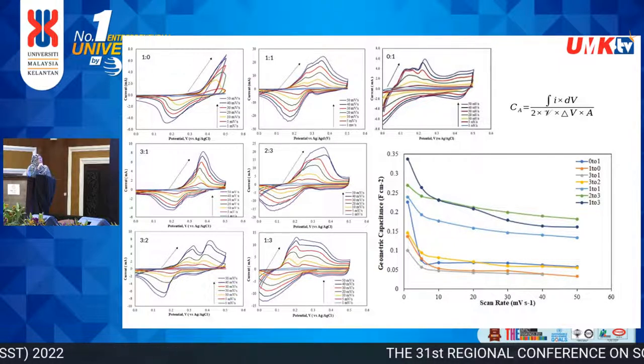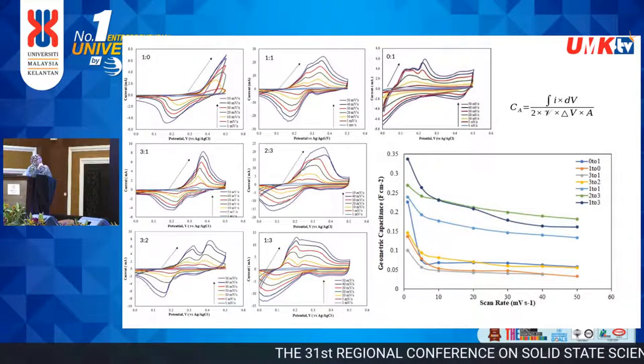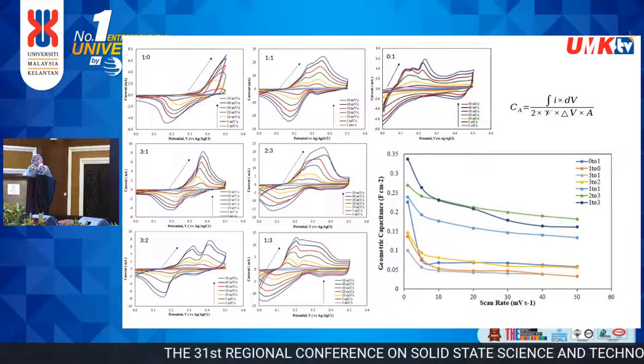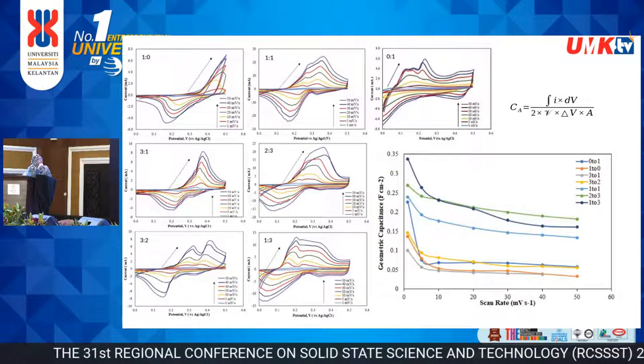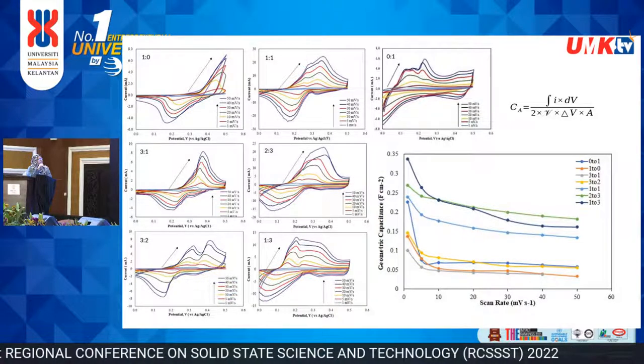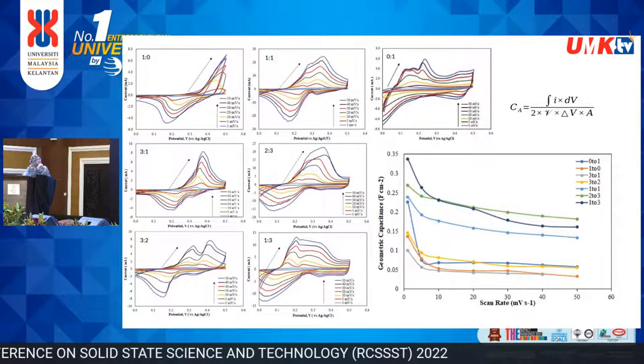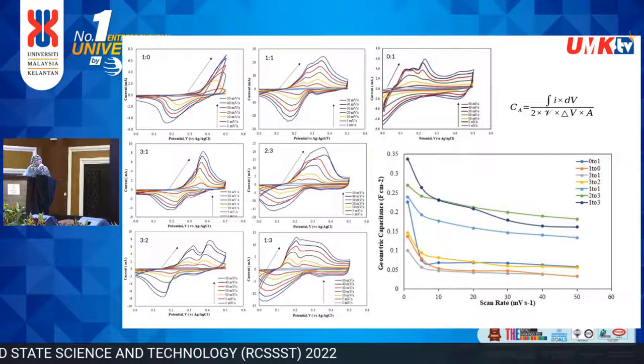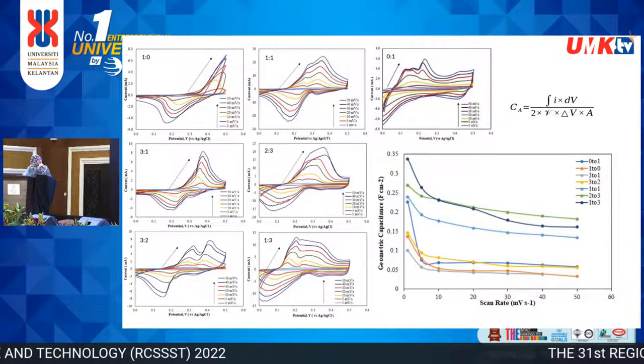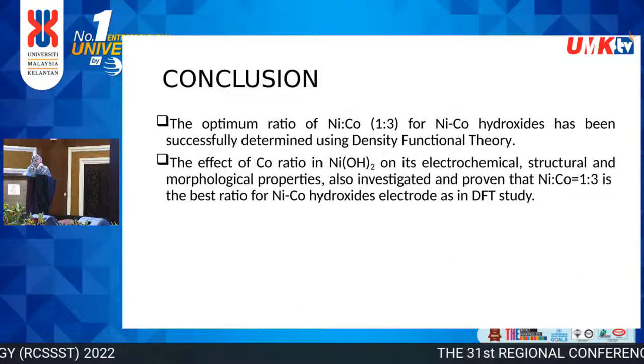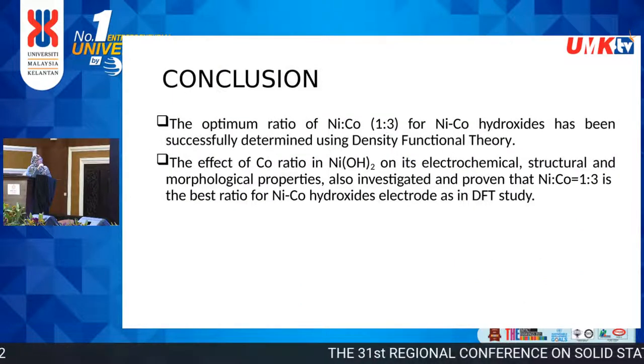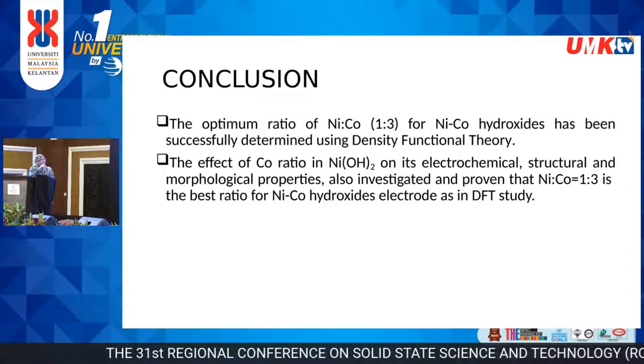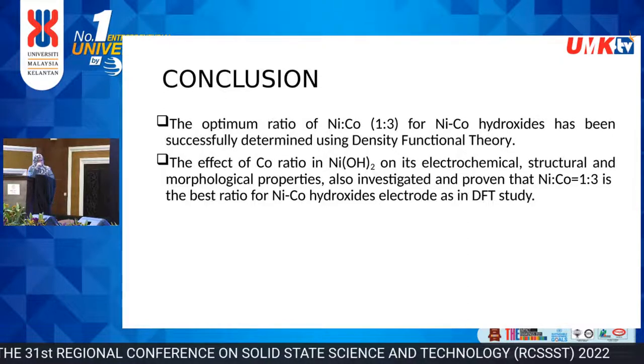Okay, as conclusion, the optimal ratio of nickel cobalt for nickel cobalt hydroxide has been successfully determined by using density functional theory. The effect of cobalt ratio in nickel hydroxide on its electrochemical, structural, and morphological properties was also investigated and proven that nickel cobalt 1-3 is the best ratio for nickel cobalt hydroxide electrode, as in the DFT studies. Thank you.